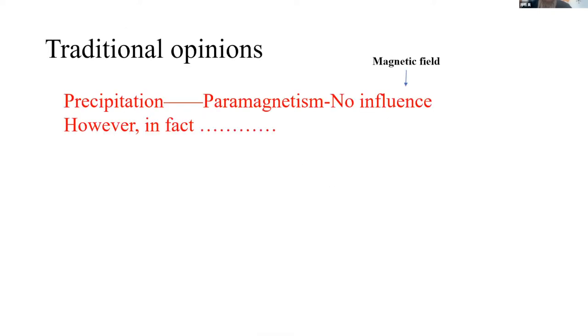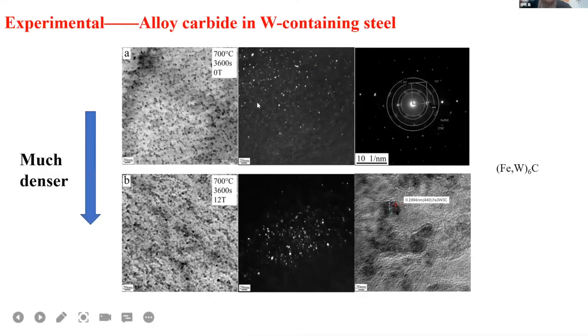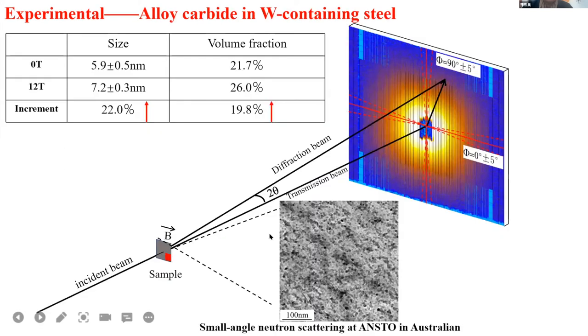Another interesting thing is about precipitations. Similarly, the alloy carbides, such as M6C, in general should be paramagnetic. But in our experiment, from A to B, the precipitates appear much denser. And we used small angle neutron scattering at ANSTO in Australia to get the result.